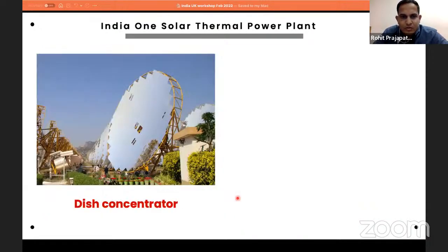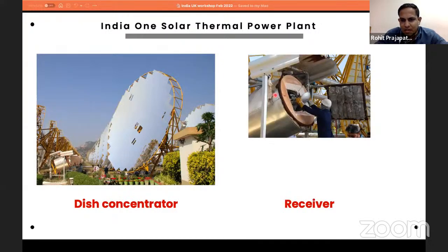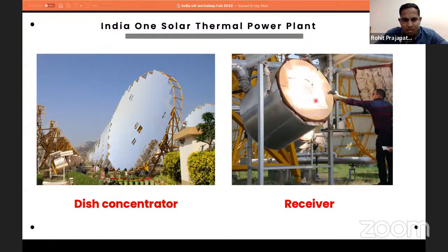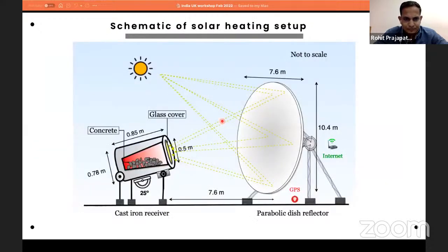So we have tried to change the heating mode and try utilizing the solar energy, concentrated solar energy. So we have transported the concrete to India One solar thermal power plant in north of India. And this is the dish concentrator. And then you can see there is one receiver, small receiver here. So we loaded this material and we have monitored the temperature, and we have tried to use the same optimized parameters that we were using in the conventional or electric furnace heating. So the sunlight is concentrated and it is focused on this receiver, and you have the material inside, and you can cover it with the glass cover to reduce the convection losses.